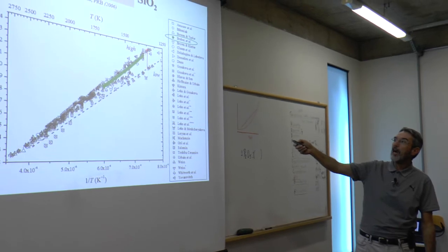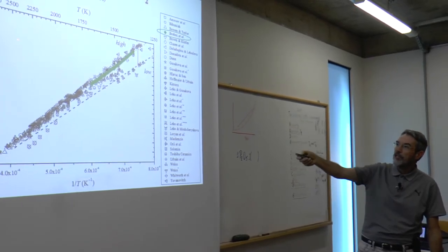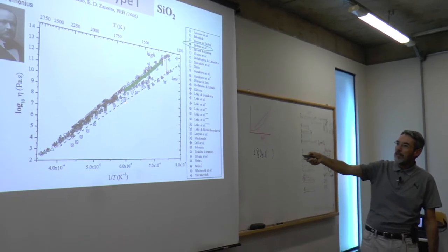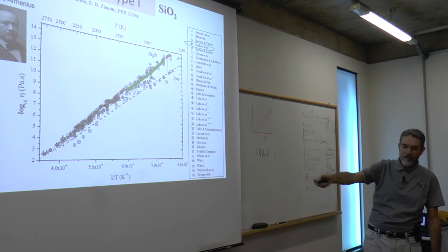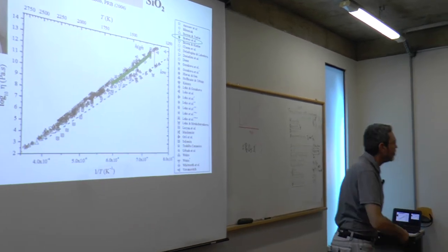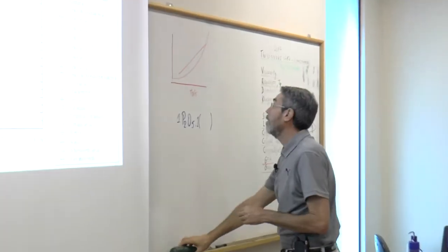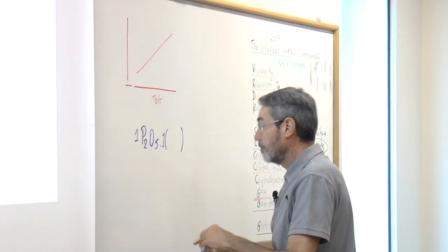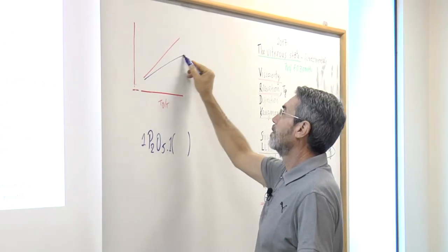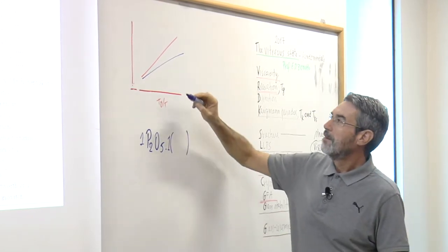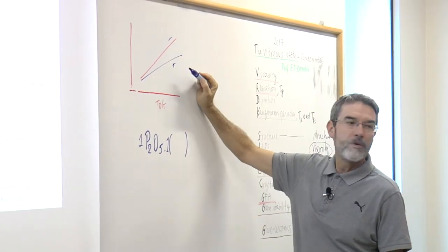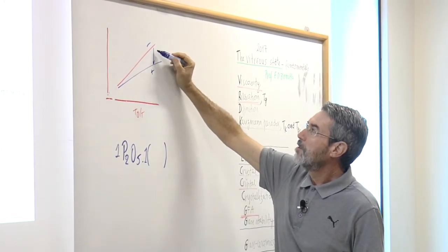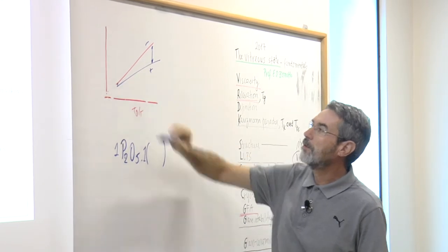And the effect is larger here, close to Tg. This is Tg, right? 10 to the 12 is Tg, than here at the liquidus. So the effect at the liquidus is not so intense. It's like if these curves are more or less like this. See, more impurities, less impurities. The difference here is 2.5 orders of magnitude. Here it is only 1 or 2 times.